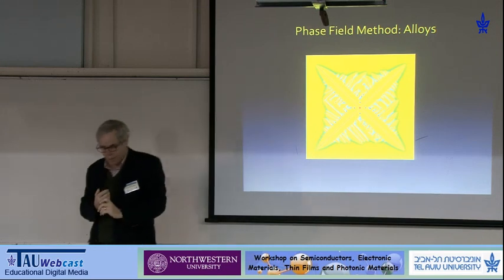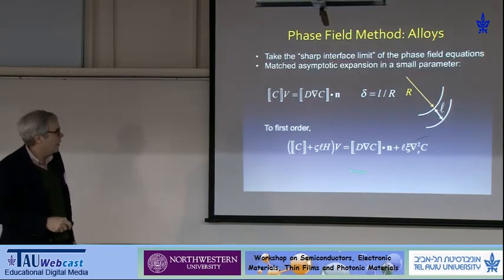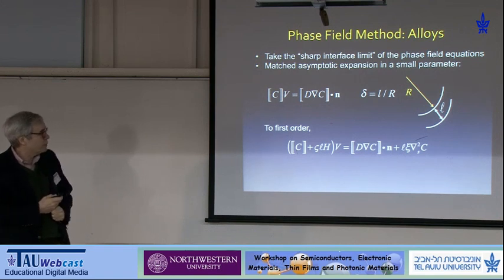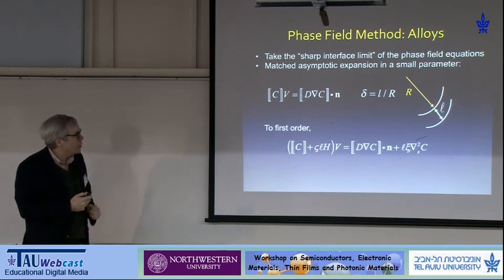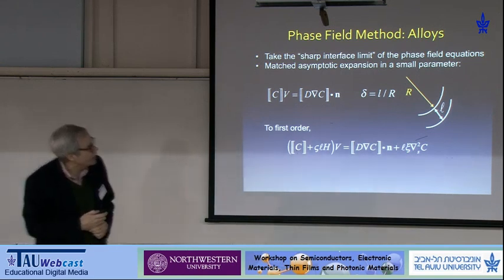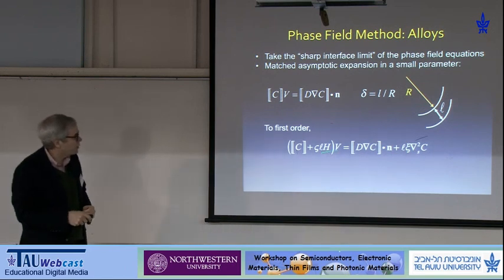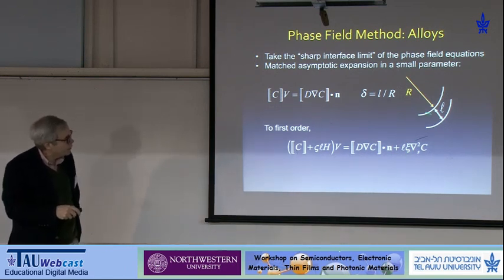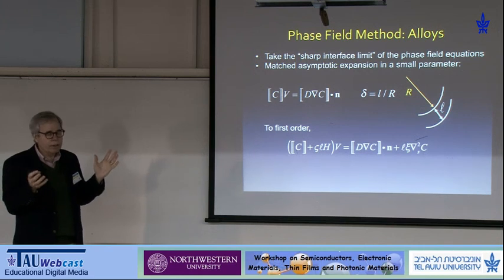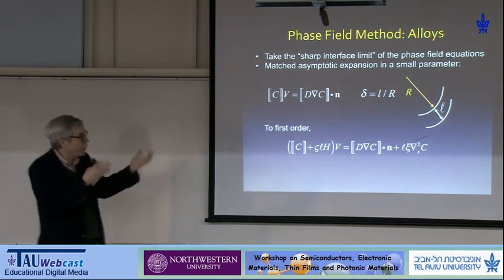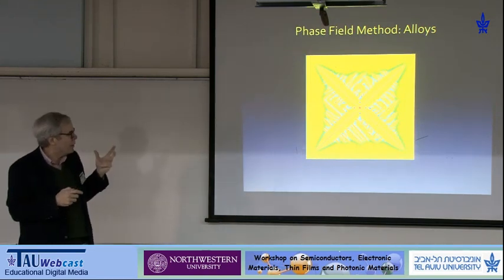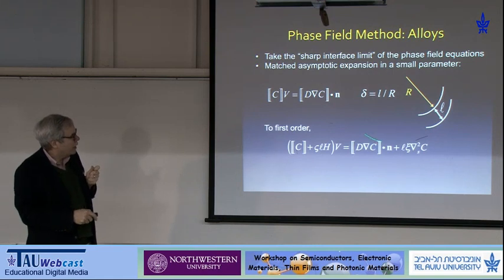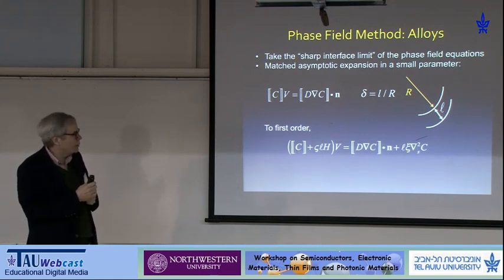So they don't have that problem. But they have this far more subtle problem that, because they didn't do the matched asymptotic expansions, they didn't know that these terms existed in their calculations. And so the idea here, and I think I'll conclude, I'll stop with this slide, is that this thickness, which allows you to do all this marvelous stuff, in other words, topological transitions, very complicated morphologies, you can follow very, very easily, comes with it this penalty of extra terms in the diffusion equation and other situations that you have to watch out for when you're actually doing the calculations.